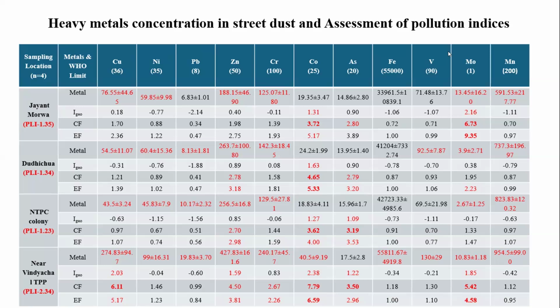So from the slide, we can see that metals such as copper, nickel, zinc, chromium, molybdenum, and manganese are high in every location. The location near Vindhyachal thermal power plant has a very high PLI, that is the pollution load index, of 2.34. The metal concentration and Igeo, EF, and CF factors are also high in this region as compared to the other regions.